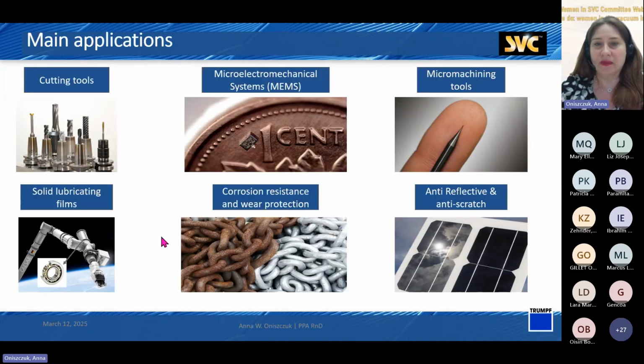And here is some research comparing HiPIMS and cathodic arc, and the mechanical and corrosion properties were much better. So here is the corrosion: A is the bare substrate, B is the cathodic arc, and C is the HiPIMS. Also, in the imprint, we can see there is much less damage. And from the scratch test, we can see that the load is much better and the roughness is much lower. So that's just one example. And then the applications: there are a lot of applications that are limited here by time, but the main ones were cutting tools and also anti-corrosive properties of the coatings.